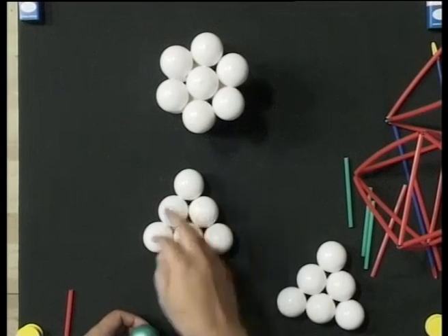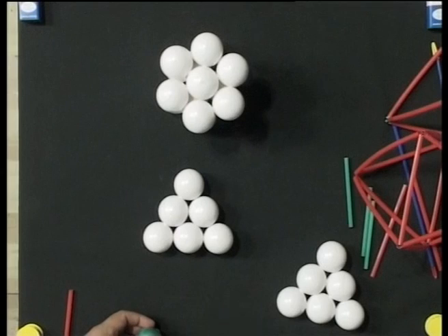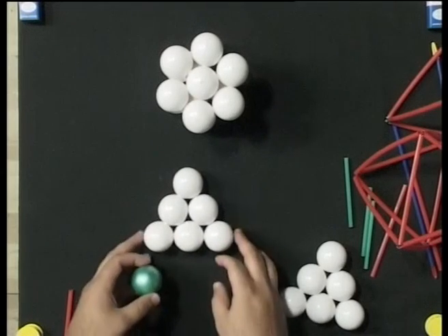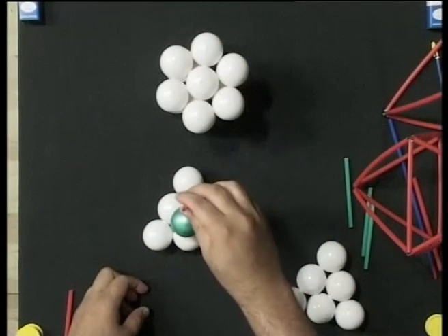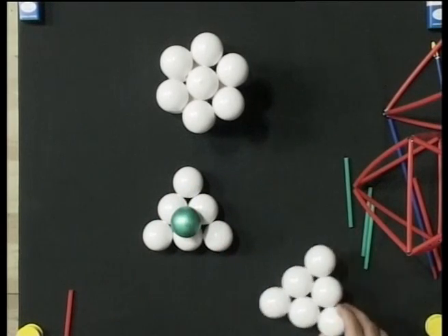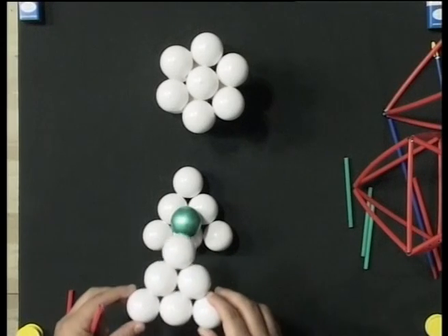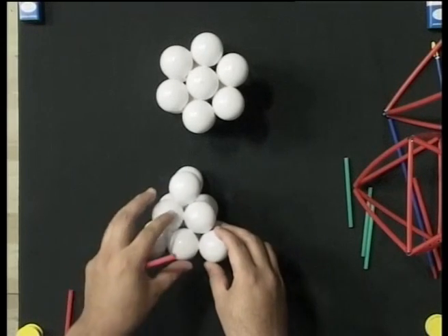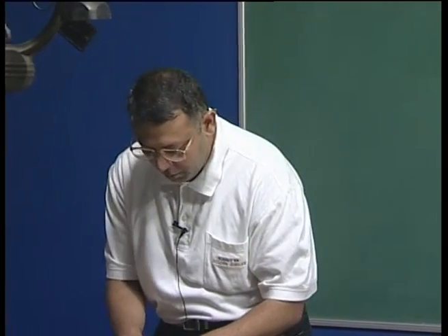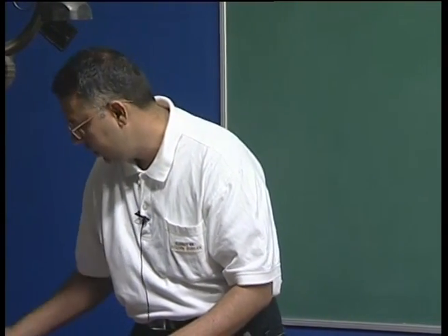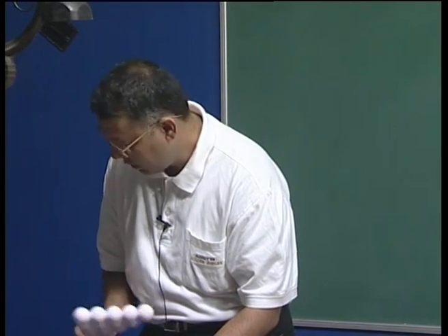So, here we have, as before, a truncated part of the hexagonal layer, and I call this the A set of atoms. So, I put my atoms in the B position, and that means that I leave my C position, which is here, vacant. Now, to make the third layer, I will take the same set of planes and put it exactly above the A layer, and therefore I get an AB kind of packing. I will continue this ad infinitum. In other words, the fourth layer would be exactly above the layer above that, and the fifth layer would again be a layer which is above the A layer, which is what it would look like this.